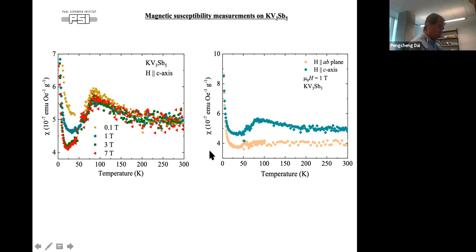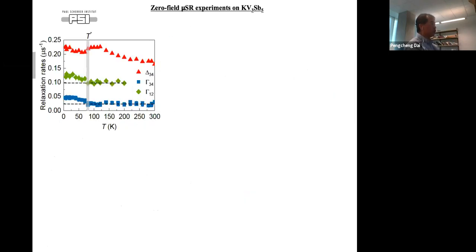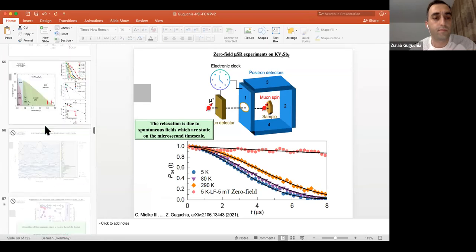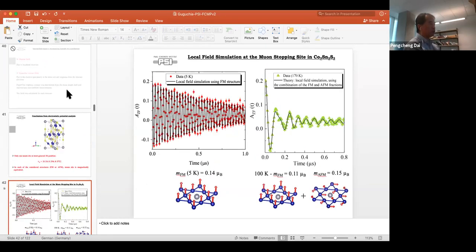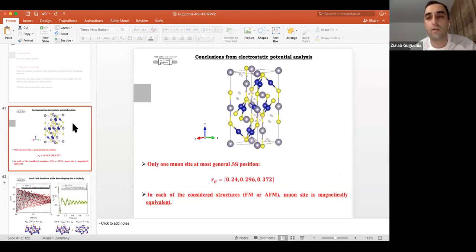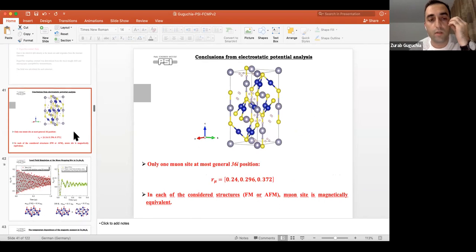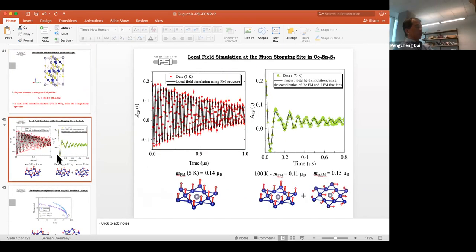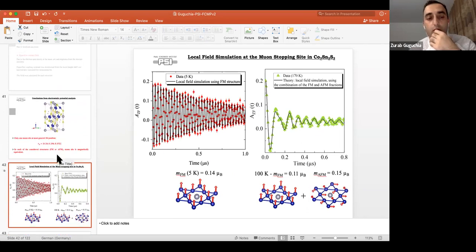I have another question. In your earlier talk, you talked about the phase separation in cobalt tin sulfur, just below the magnetic ordering temperature. How do you understand this, considering the material has the same crystal structure? How can you have two different magnetic structures? Exactly, the crystal structure we see is the same, but we never measured local structural distortions. So you think the local structural distortion is slightly different between the two parts? Yes, this would be my guess, and there is a strong coupling between structure and magnetism, because when you cross the magnetic transition temperature, you have a change of the Gaussian and Lorentzian widths in the neutron diffraction pattern. So you clearly see that somehow the structure is coupled to this magnetic domain.